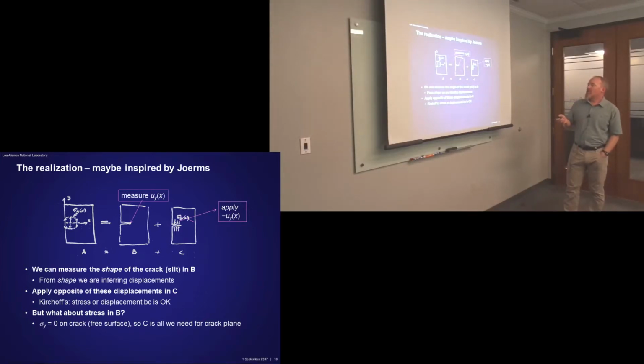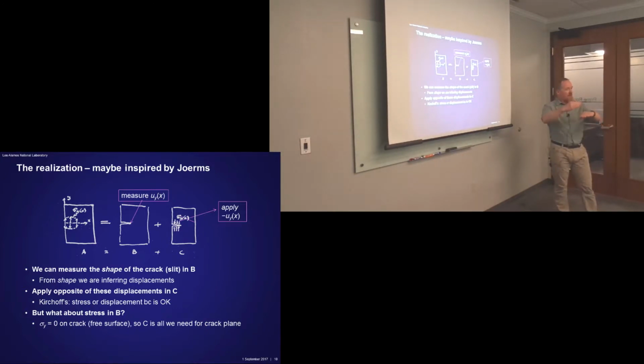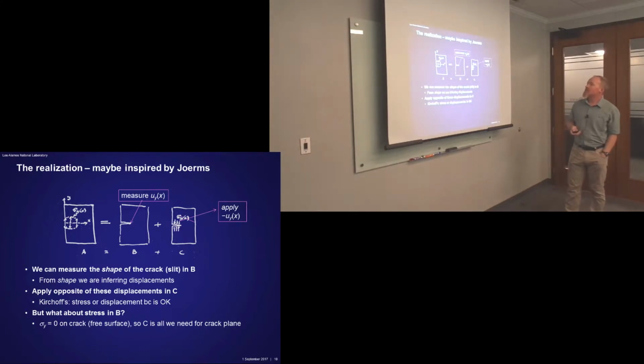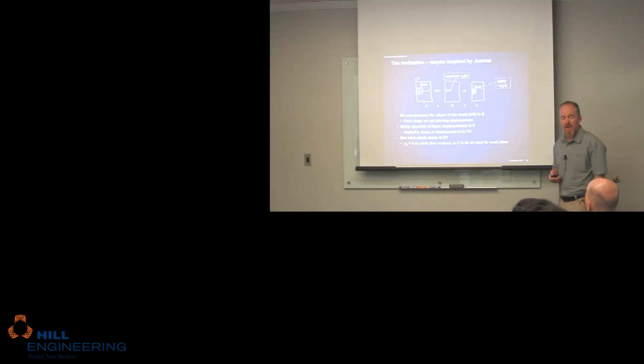And I realized, of course, right away, that if you did that, you could measure displacements all along that cut face and not make a 2D assumption, but get a 2D stress field in a 3D part. So that was kind of where the idea came from, was actually looking at this figure from a slitting paper. What about the stresses in B? There's 0 on the cut face for that normal stress. So this alone will give you that stress on the cut face, which is why it should work.